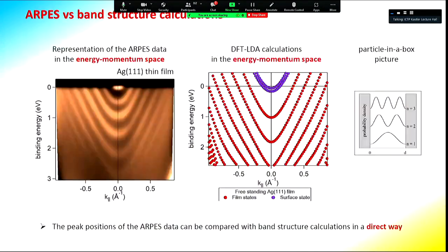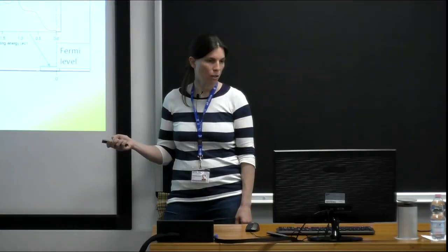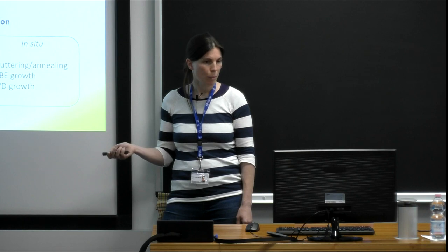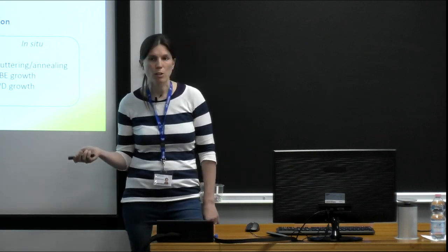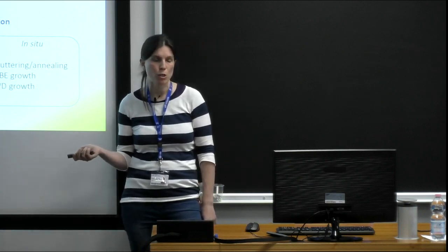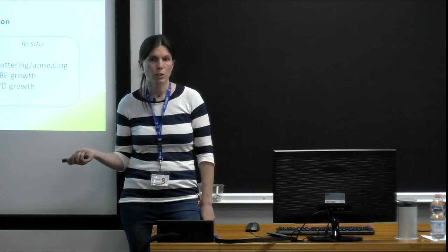At these photon energies, photoemission probes can go about 2 nanometers, that means up to 10 atomic layers.